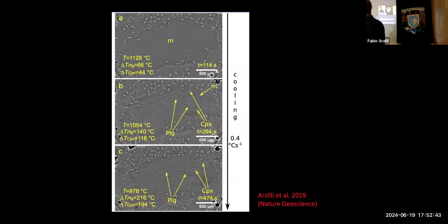So we start from a magma that was partially crystallized with this pyroxene and oxide. This is a pocket of melt. It's a pure melt here in the middle, and then during these experiments we imposed a very fast cooling, 0.4 degrees per second, so 24 degrees per minute, simulating a fast perturbation of undercooling, cooling down our system quickly. And so you see from time 114 seconds to time 294 seconds, more or less 3 minutes, you can observe plagioclase and dendritic pyroxene growing around them. After another 3 minutes, it is completely crystallized.